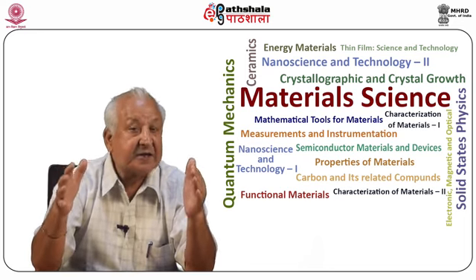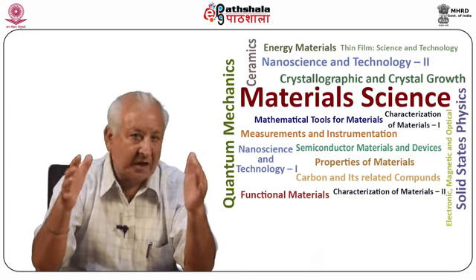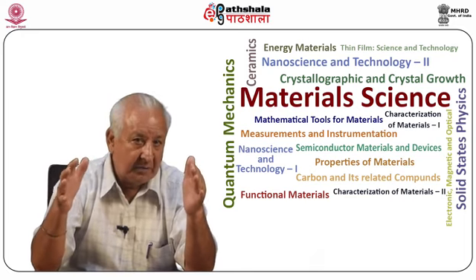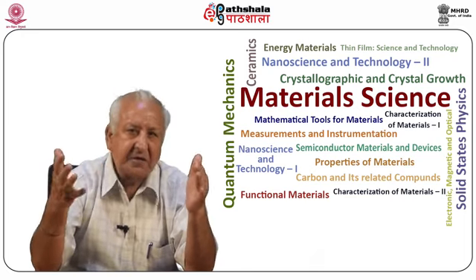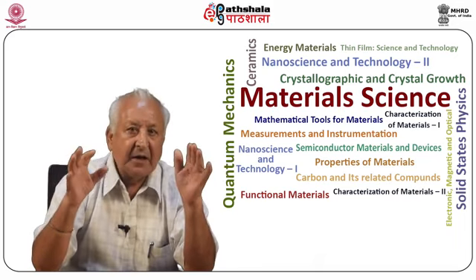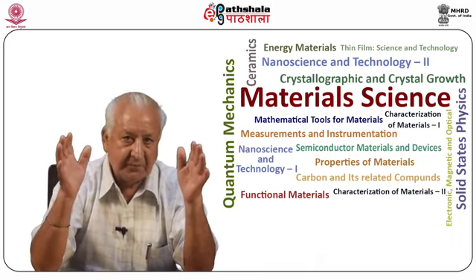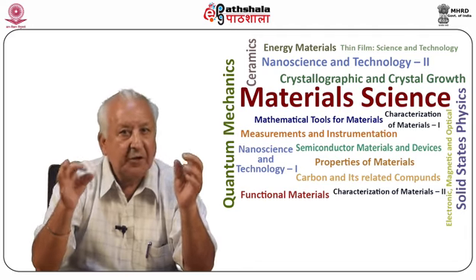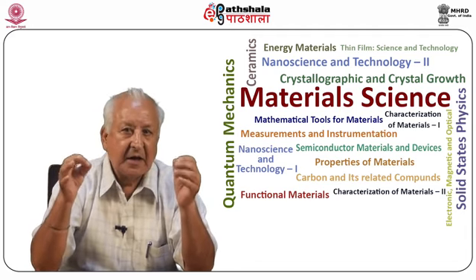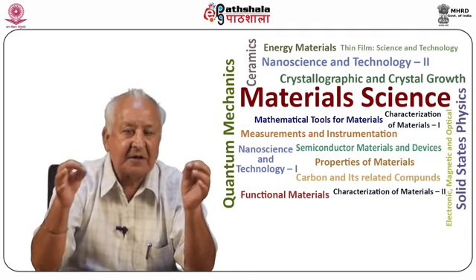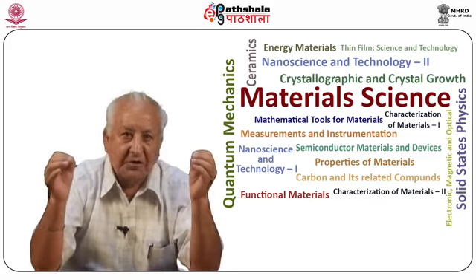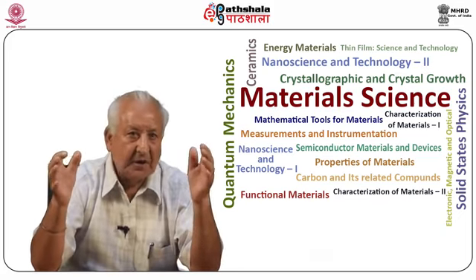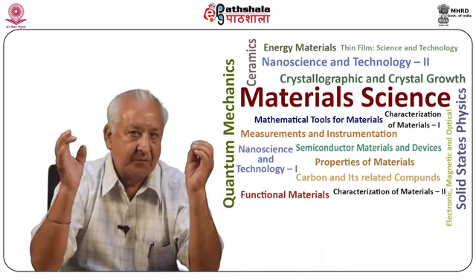Its solubility is extremely large. One can therefore make a solution of alum by taking approximately 15 grams of alum in 100 milliliter of water. Put this solution into a beaker, heat it while stirring constantly and vigorously. The hot solution may be filtered to obtain a pure solution.